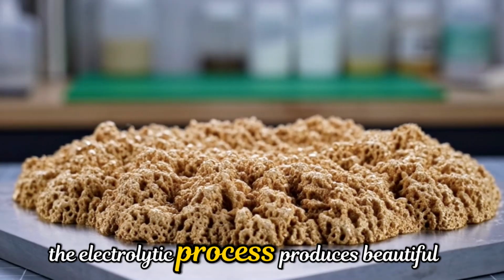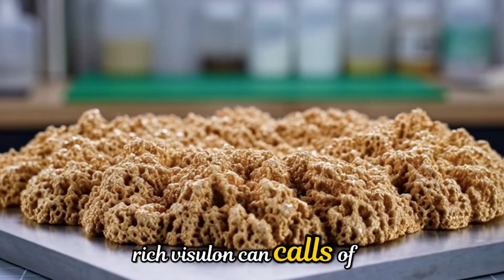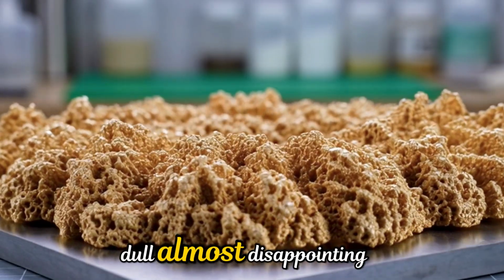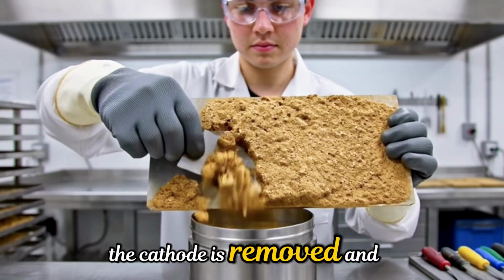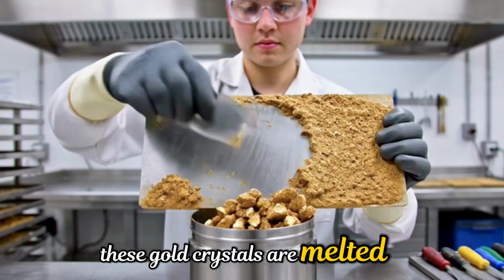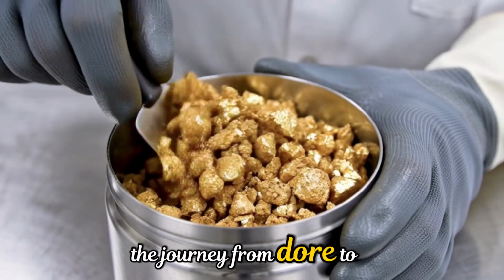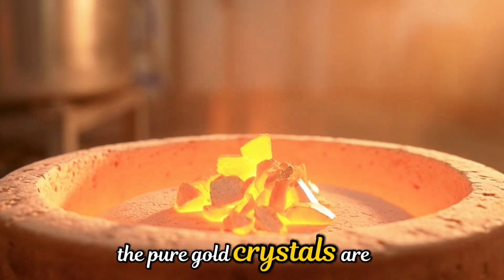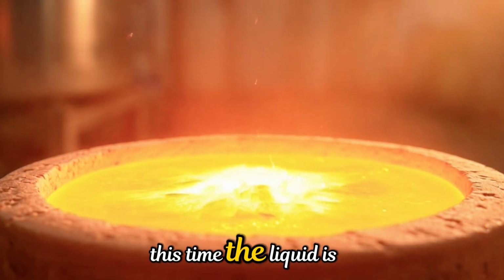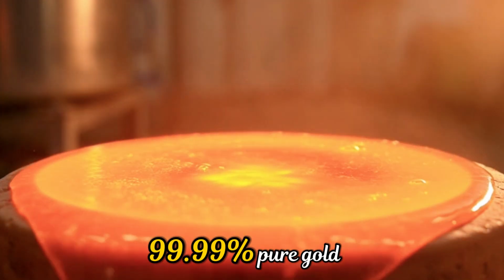The electrolytic process produces crystals of gold, rough, dull, almost disappointing. The cathode is removed and the gold crystals are scraped off. These gold crystals are melted and poured into final bar molds. The journey from doré to pure gold is complete. The pure gold crystals are melted once more. This time, the liquid is 99.99% pure gold.